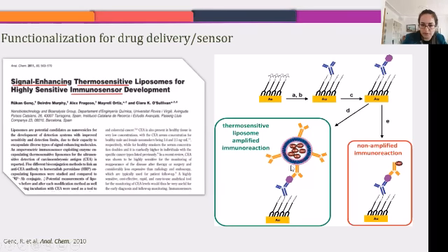Liposomes are lipidic materials that have a hydrophilic core on the inner side, and they have a surface which can be modified with other materials. So I designed a liposome for this purpose, which can encapsulate many enzymes at once. I also designed a surface for them, which enables the attachment of the antibody in the right orientation, so that it can see the antigen and attach to it.